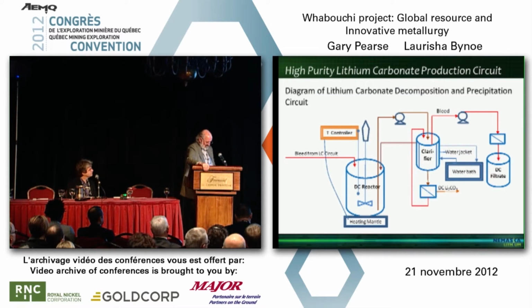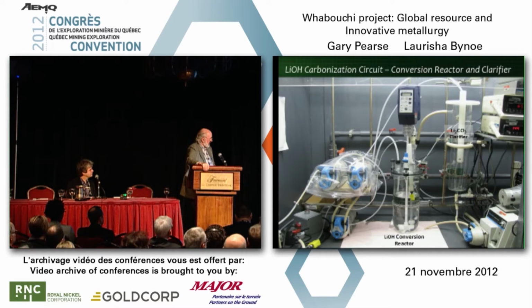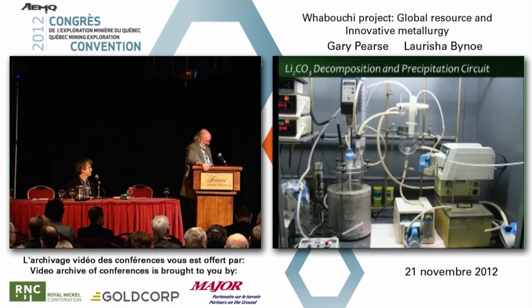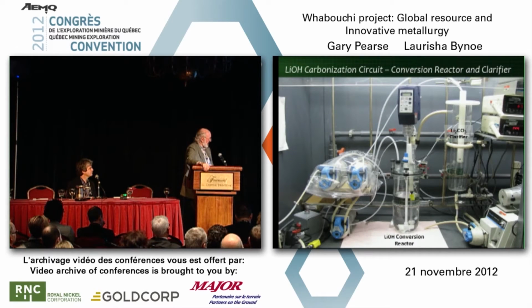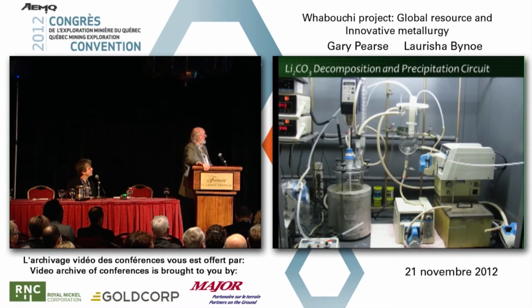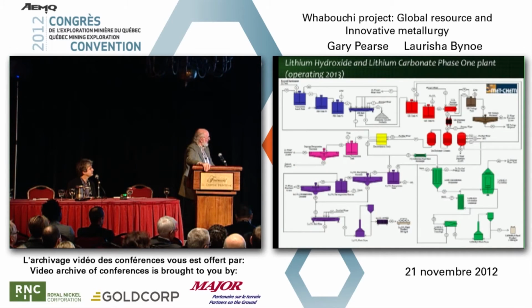And overall, the efficiency of that process is 97.3% efficient in recovering lithium carbonate. This is the laboratory lithium conversion reactor, lithium hydroxide, and they call it decomposition precipitation circuit because you have lithium bicarbonate in solution. You heat it up, drive off the carbon dioxide that it took with it, and it'll then precipitate again. This is a demonstration plant that will be up and running in 2013.